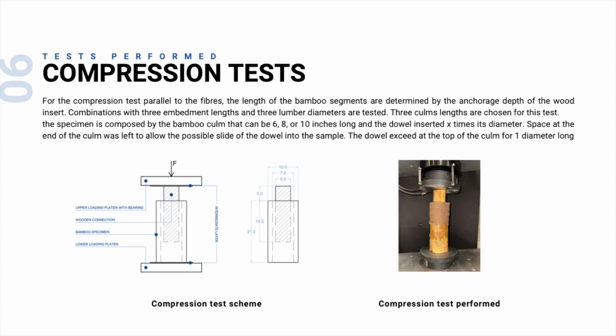So in the compression test, the bamboo segments were prepared with different lengths according to the anchorage depth of the dowel. So we tested a combination of 3 different dowel diameters and 3 different anchoring lengths. And the dowel was glued inside the cane, but a small portion was left outside of the bamboo culm, so we could observe its behavior during loading. And here the main questions were, does the anchorage length really matter? Or is the diameter of the dowel the critical factor?